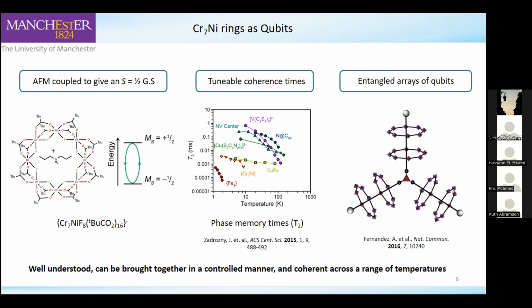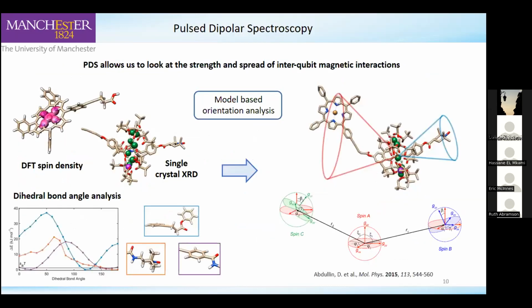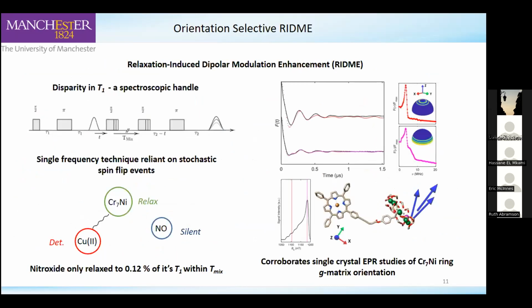And then a related question: when you were analyzing the pulse dipolar data, the RIDME, did you take into account the size of this cluster? Because this is certainly not a point dipole. Yeah, so our orientation-dependent algorithm takes into account the distribution of the spin density on our centers. So it was modeled as 8 points of distributed spin density when we looked at our simulations. These are fits, but they're simulated fits from the library of simulated compounds, and the spin density is explicitly taken into consideration there.